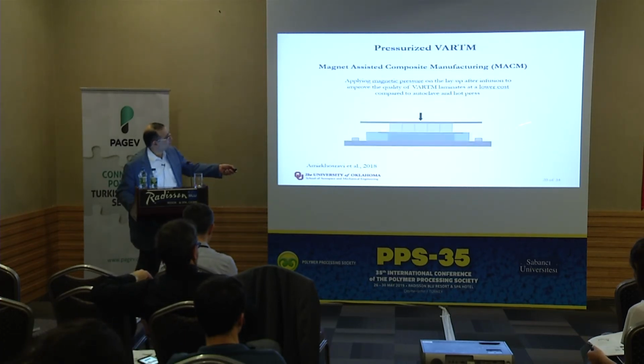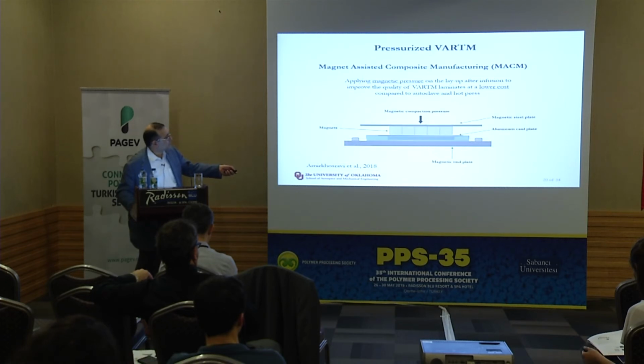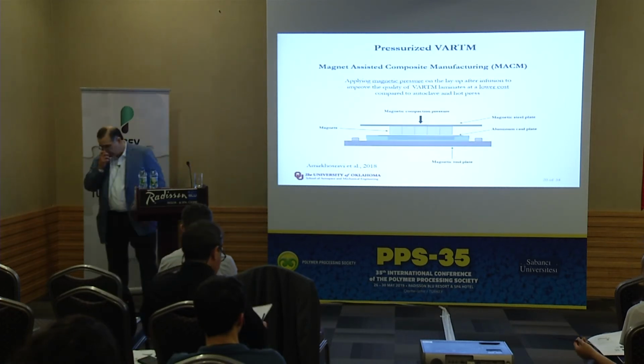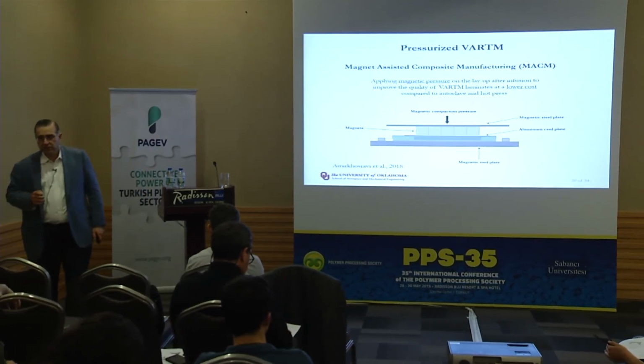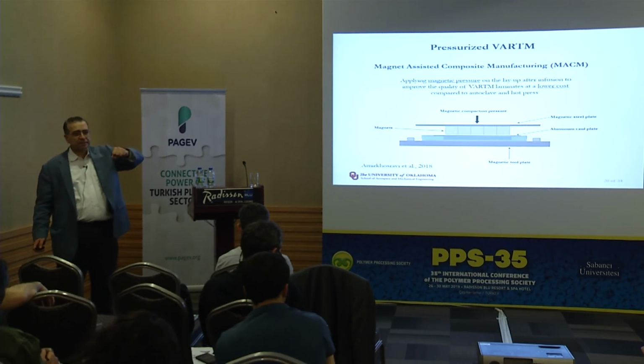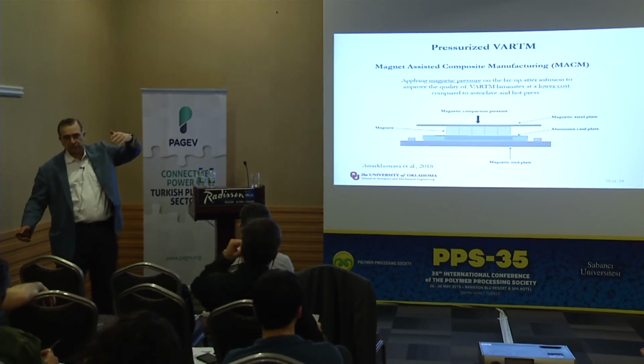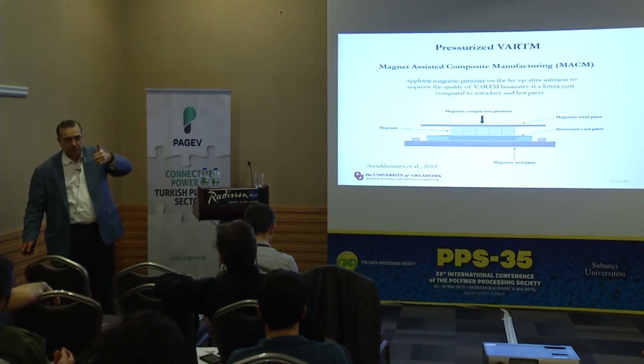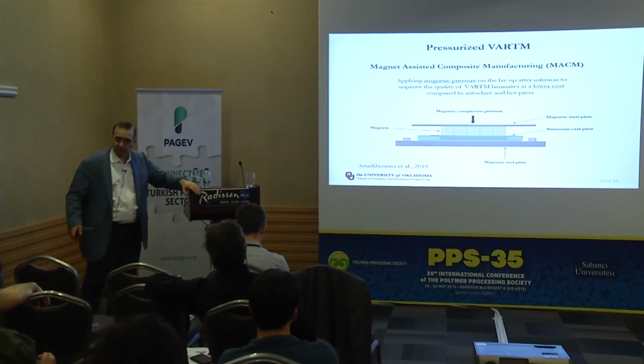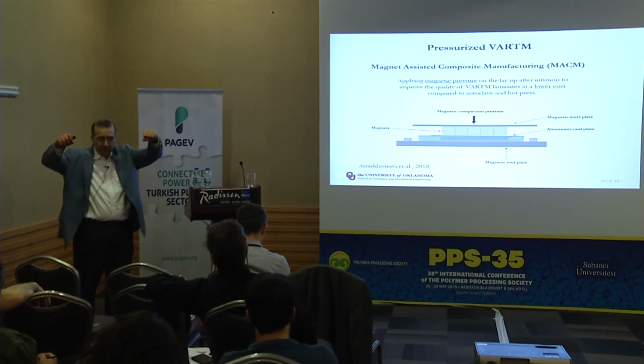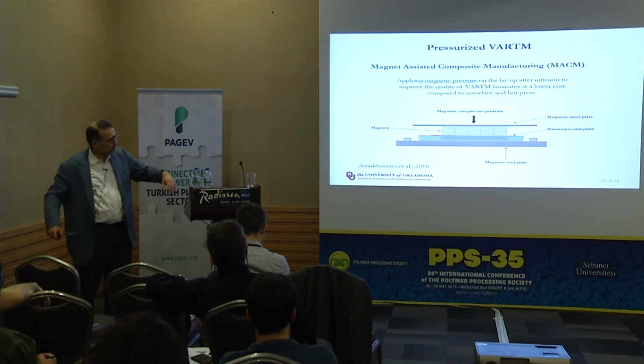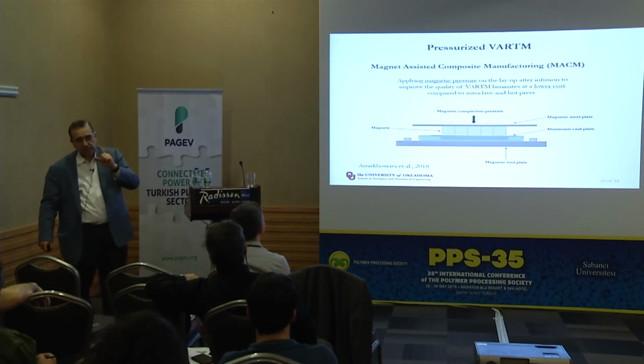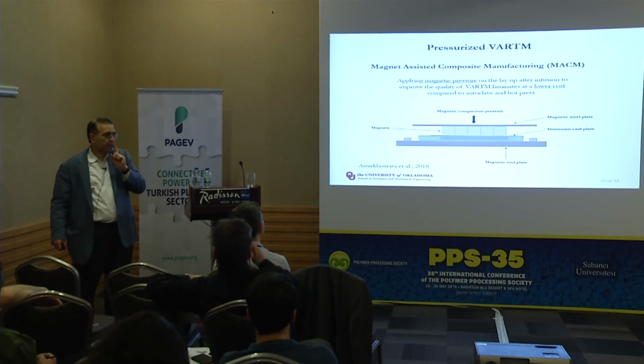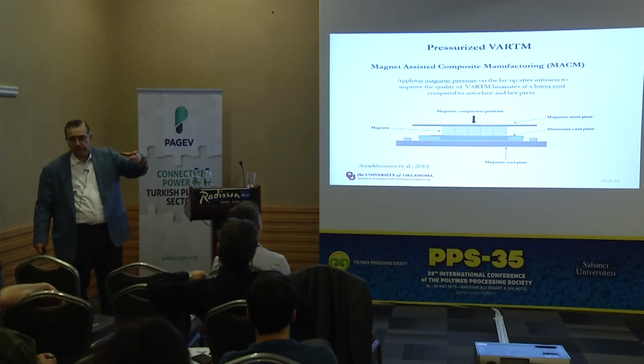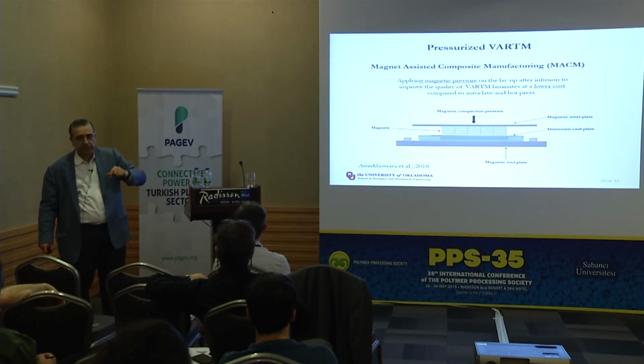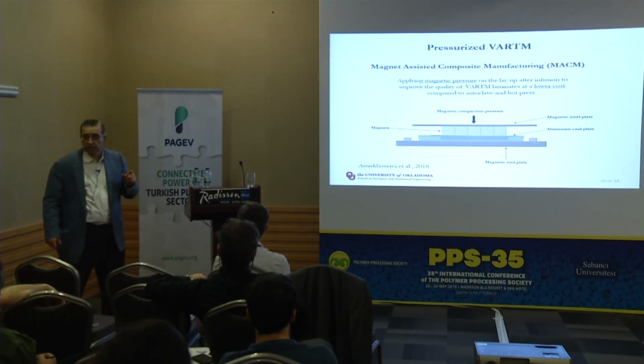So you essentially, if you have a magnetic plate, you can generate 100 psi with the magnets. Right? You have those magnetic lifts that you can lift steel plates in the machine shops, right? Those are either electromagnets. For used cars, before they scrap it, they lift the car with the electromagnet, right? Or in metalworking. So those magnetic lifts essentially rated based on the force they generate. But for composites, you can look at their cross-sectional area and divide the force by area, and you can calculate the pressure they can apply.